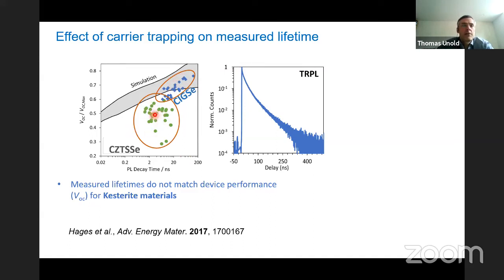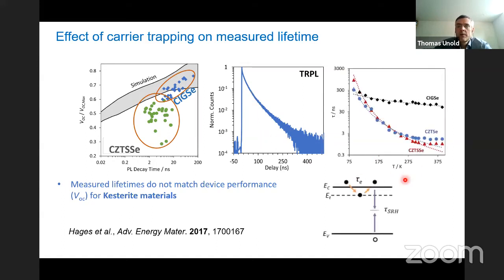So the measured voltage was way lower. And we looked at this in detail. So here's a typical transient shown. So usually people measure lifetimes of maybe 10 nanoseconds or so. And what we found, to make a long story short, is that there was a significant effect of trapping and detrapping here. So you photoexcite carriers, and then they were falling into shallow traps, and then it takes time for them to come out thermally.